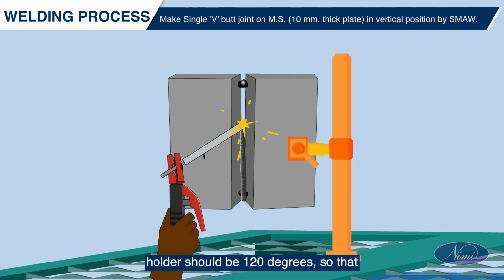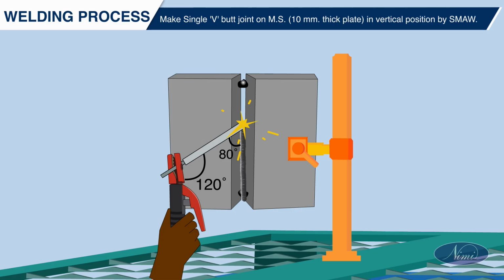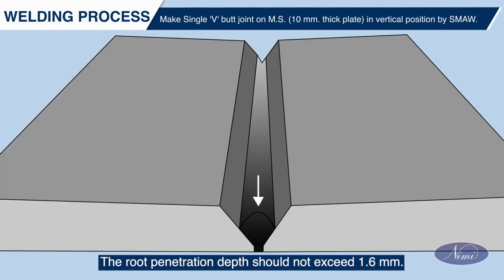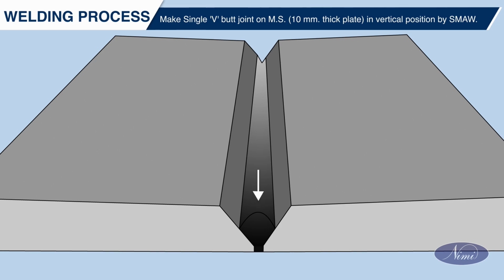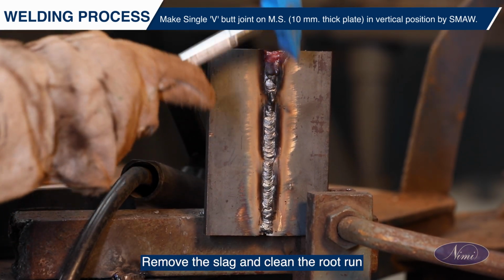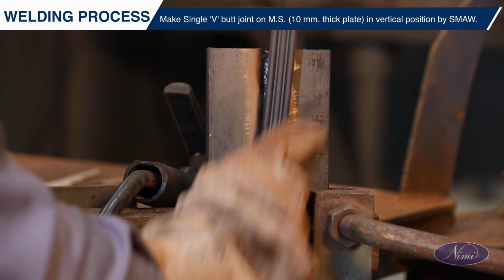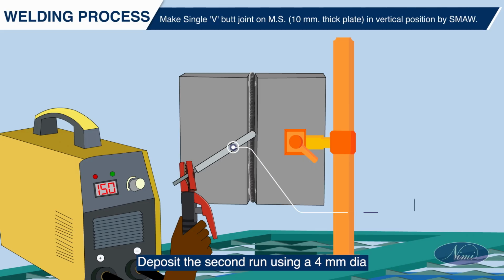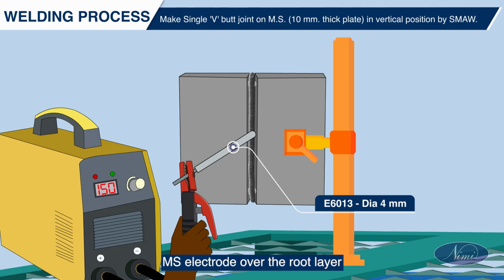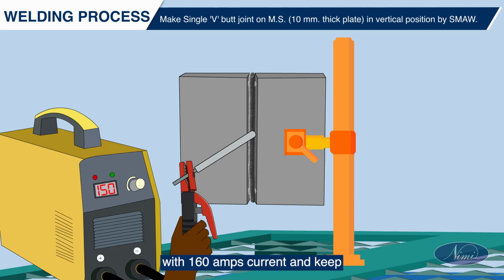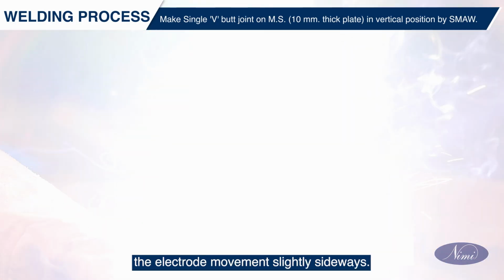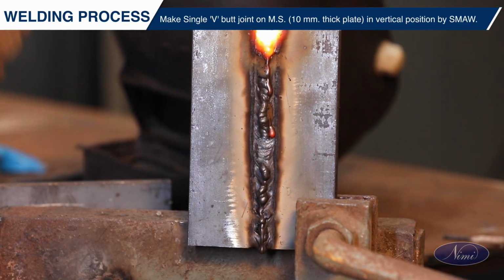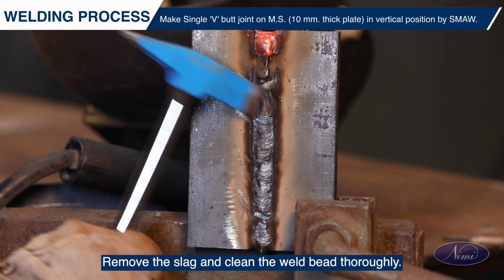The angle of the electrode in the holder should be 120 degrees so that it is convenient to hold the electrode at 80 degrees to the line of weld. The root penetration depth should not exceed 1.6 mm. Remove the slag and clean the root run by using a chipping hammer and wire brush. Deposit the second run using a 4 mm dia MS electrode over the root layer with 160 amps current and keep the electrode movement slightly sideways. Remove the slag and clean the weld bead thoroughly.